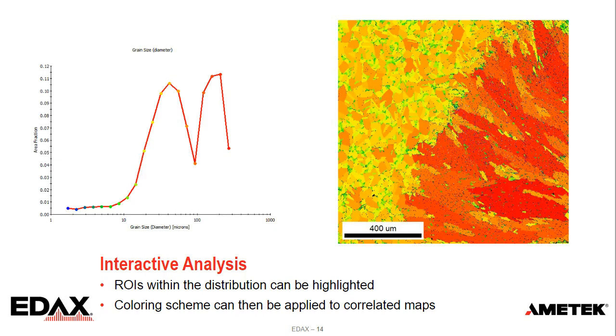The other thing I'd like to point out to remember, with EBSD, we have the choice of including or excluding the edge grains. These grains that we see that are touching the edge, we're not measuring the full grain. So mathematically, you probably don't want to include them in your distribution. But from a map, it makes it look better to color to the edges. It looks a little weird if you throw them out. So that's why I've shown them this way. But if I'm trying to extract it correctly, I generally will exclude those.